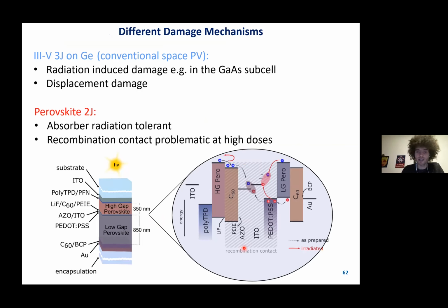So if you imagine the recombination layer is formed by this C60 and then some TCO layer and PEDOT:PSS. So if this recombination layer is damaged, you could get all kinds of different PL variations. So you extract less efficiently, you have more recombination at that interface. And we think this is causing the damage in the tandem.